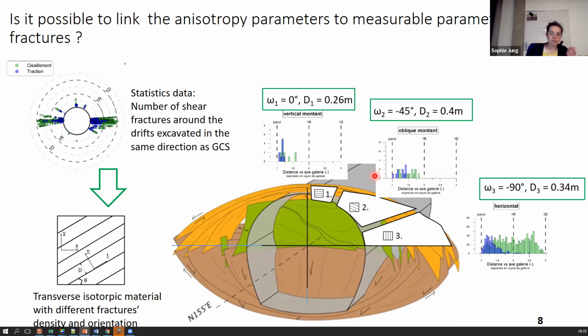So you have here the case of GCS drift, and the REV is changed, the orientation and the fracture density are changed between the different zones. The whole medium is not modeled by one material anymore, but it's cut into different zones of different fracture density and orientation. This division into different zones is done based on statistical data obtained from all the drifts excavated in the direction of the major principal horizontal stress. I will then refer to this type of model simulation as a simulation of GCS type drift. So it's all the drifts which present a horizontal fracture zone.